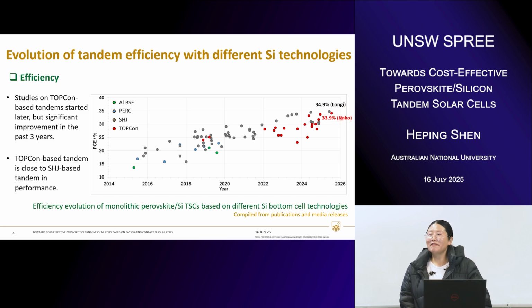But silicon heterojunction has historically, particularly in the last decade, been dominating in the perovskite silicon tandem application, and therefore leading the efficiency record. But this picture changed over the last 3 years. As you can see, a lot more red dots, which are tandems based on TOPCon, are coming up, and the efficiency is also progressing very fast, although their first report was demonstrated only a few years after that based on heterojunction solar cells. Okay, with that, I believe it's clear that TOPCon and silicon heterojunction, both high efficiency passivated contact silicon solar cells, remain highly efficient, and the efficiencies are very close, both at the single junction and also the tandem level.